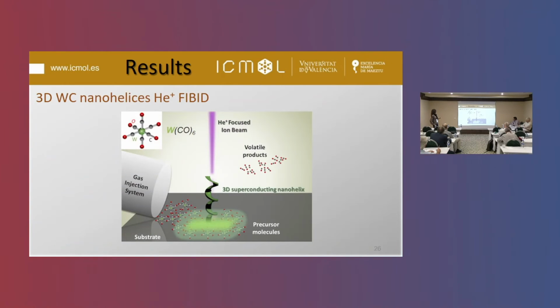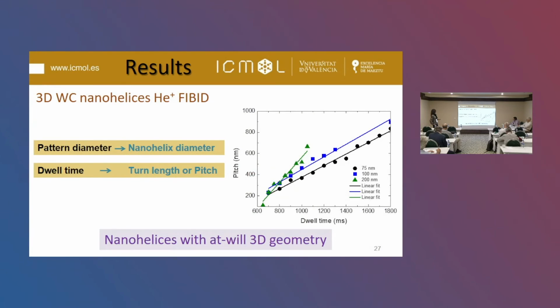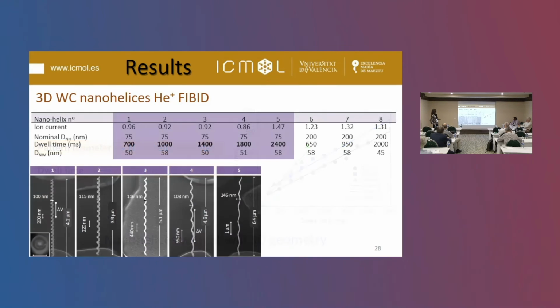So let's move into the second example, the 3D tungsten carbide nanohelices. We can see that just by modifying two deposition parameters, which is not really complex, I'm able to tune the nanohelix diameter and the turn length or pitch between them. So just by modifying these two parameters, I'm able to grow nanohelices with at-will three-dimensional geometry. And here I show you a few examples.